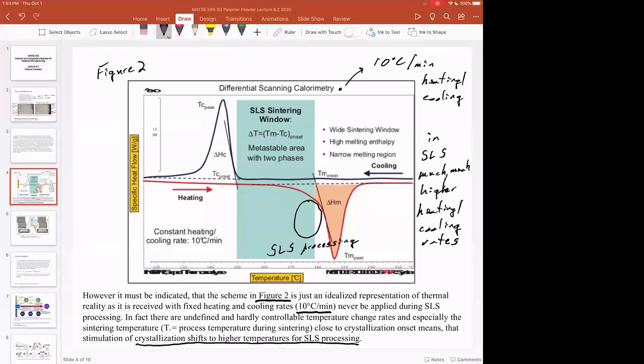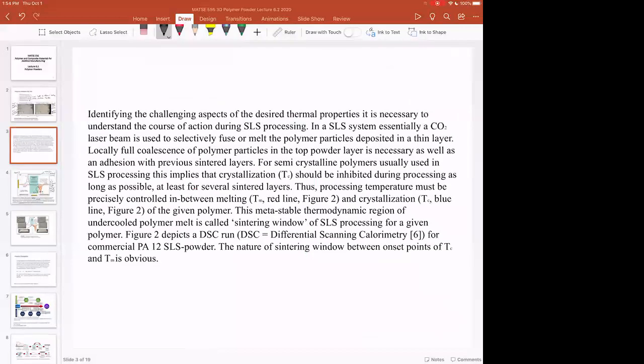So you really want to be close to that melting. And of course, in SLS, you don't get to control the temperature precisely. And so even though this is still an idealized schematic, lots of things can be happening in terms of what's happening in SLS, how the laser is controlled, and that's why you have to optimize the scan speed, the laser power, all of those things, whereas this DSC just gives you a guide as to what's going on.